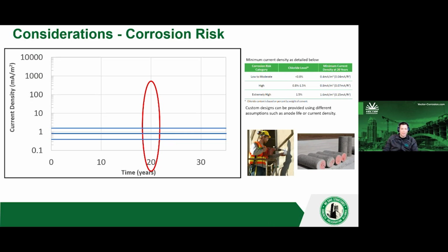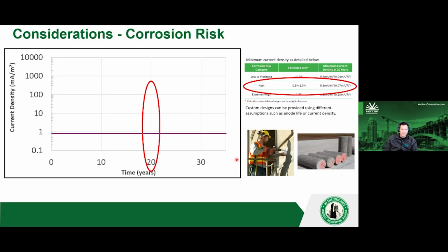So in this case, the corrosion risk was high, so we know what we need to aim for. 0.8 milliamps per square meter at year 20. Because once our current level drops below this 0.8 number, corrosion can reinitiate. Even though we're providing current, corrosion can reinitiate based on chloride level.